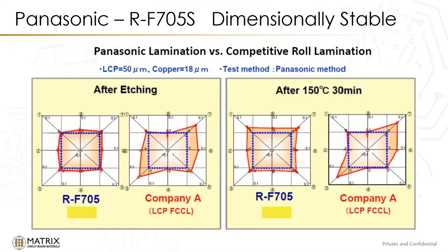The RF705 material is very stable, and this is one of the charts that's been used before to characterize that. You can see a very uniform movement after etching and then after a thermal, after 150 degrees C for 30 minutes. So this would show any of the stresses that may be inherent in the materials that may contribute to dimensional stability or instability as it would be. And so with that, you get more consistent processing.